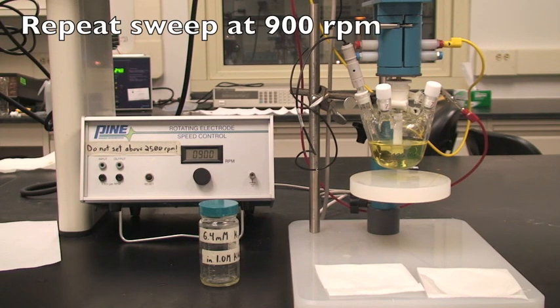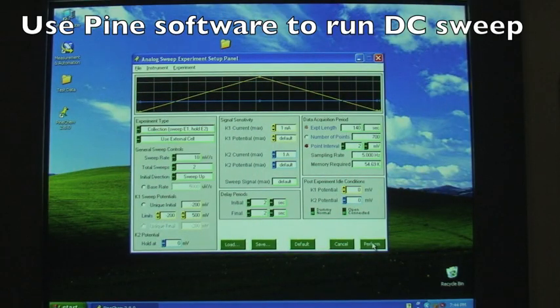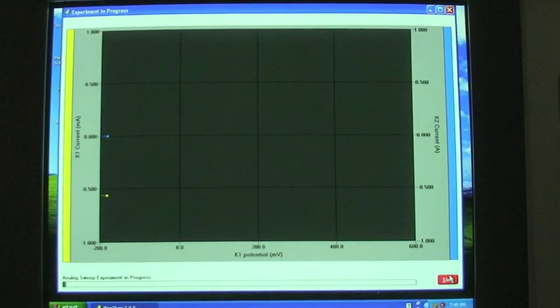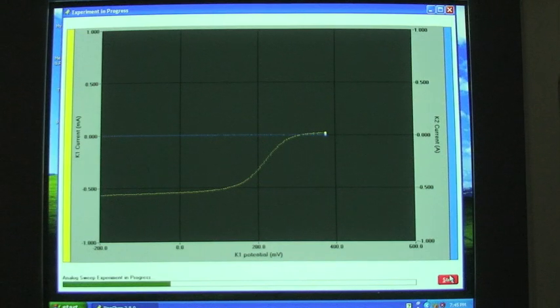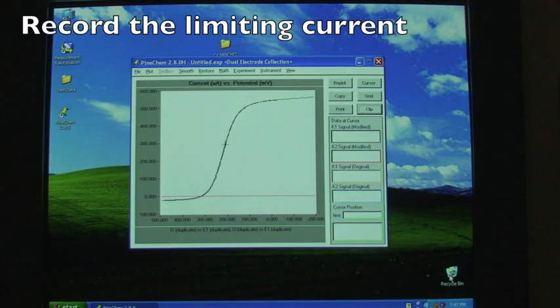Set the speed controller to 900 RPM and repeat the test. Use the same sweep settings as was used at 400 RPM. The same current behavior should be observed here, only the magnitude of the limiting current is larger. This is because the rotation of the working electrode induces convection in the test solution. In an unstirred solution, mass transport is limited by diffusion of the active species to the electrode surface. Increasing the convection increases the rate of mass transport beyond that from diffusion and thus allows a larger limiting current. As before, record the limiting current value for later analysis.